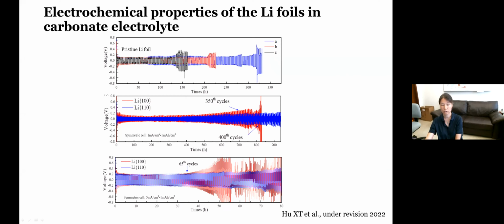But if you look at the symmetrical cells prepared with either lithium 100 or lithium 110, the results are actually very consistent. For each of the foils prepared as electrodes in the cells, you get very similar results. The red one is the 100 and the blue one is the 110. And the blue one does last a lot longer in comparison with the 100 as well as the pristine samples. And one interesting pattern observed is that for the pristine samples as well as the 100 samples, when the cell fails, you see huge fluctuations in the voltage, suggesting the major failure mechanism is the cell shorting, basically. But in the case of the lithium 110, we seldom see these large fluctuations. Instead, we see a gradual increase of the overpotential until eventually the cell fails at longer cycles.